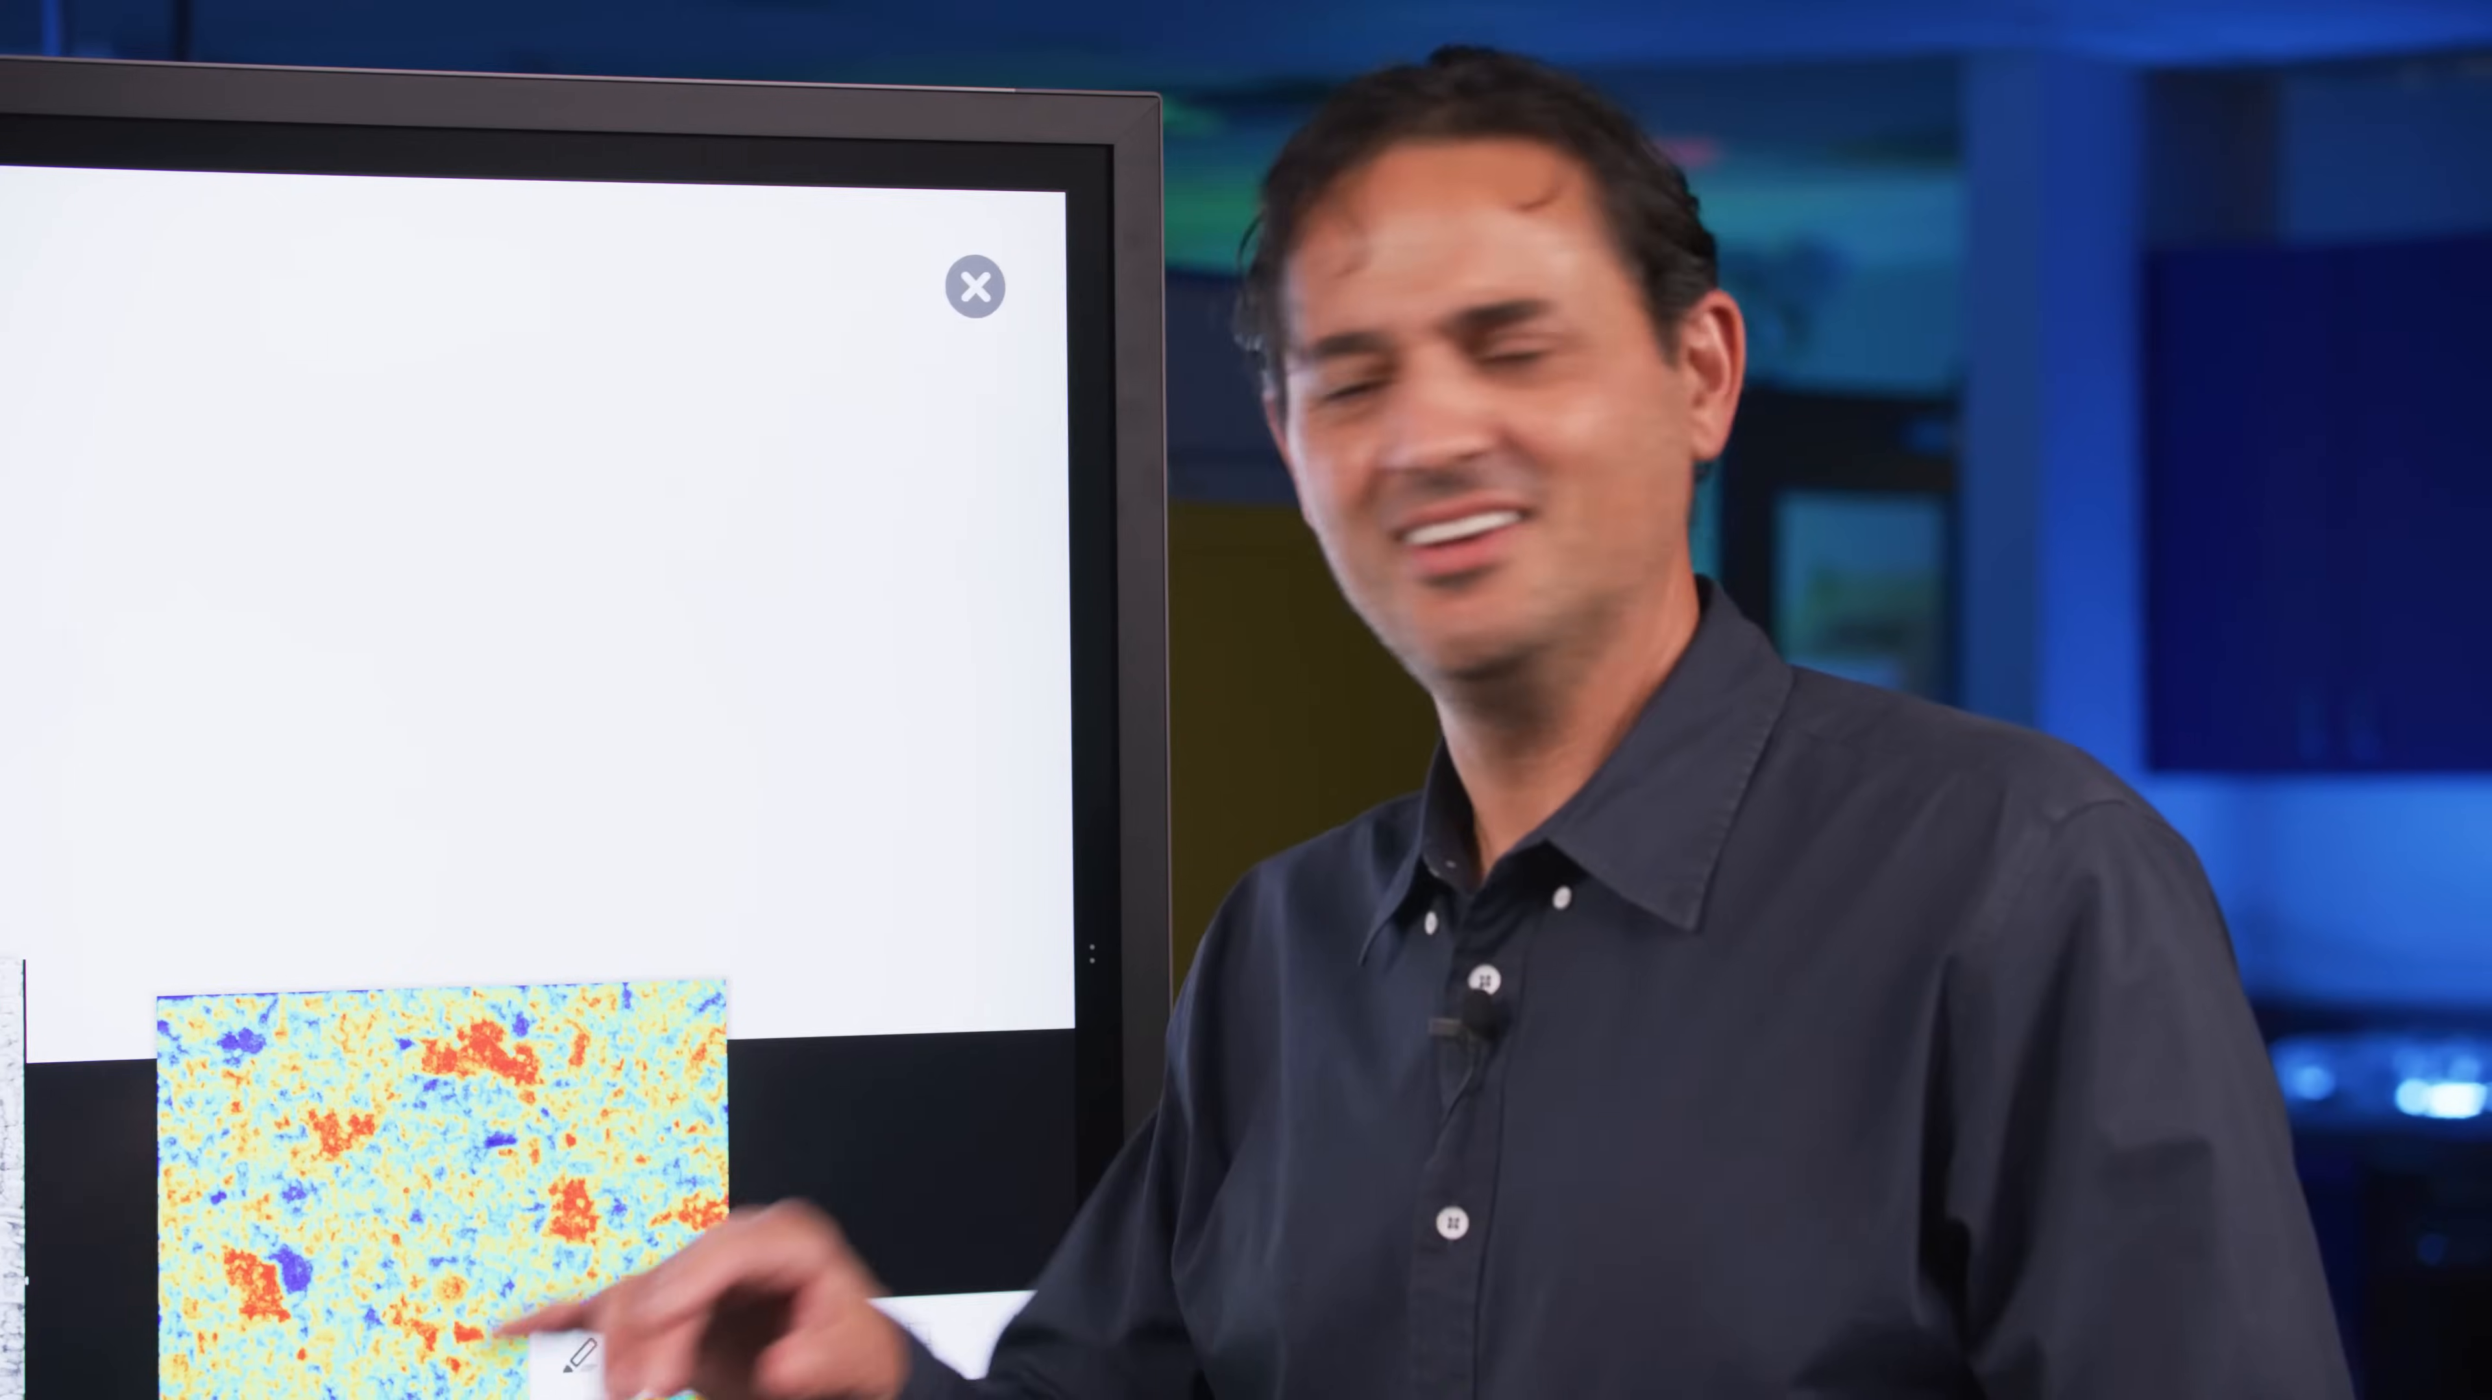This is a fully charged cell, so you'd expect all the lithium to be in the anode and not in the cathode. And here you can see some buildup of trapped lithium in the cathode.